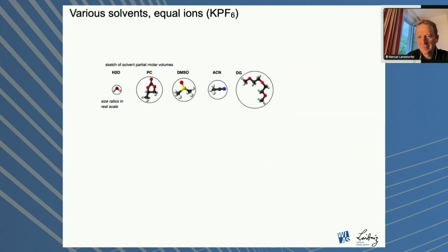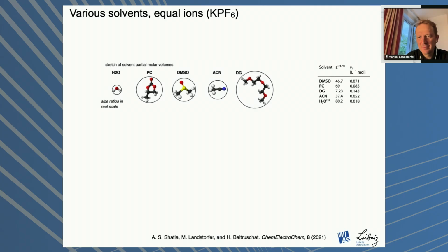I brought a colleague from electrochemistry in Germany, Helmut Baltruschat, into this, and he made experiments on different solvents: not only water, but this whole series of water, PC, DMSO, acetonitrile, and diglyme, all for the very same salt, KPF6, in order to test whether the hypothesis that monovalent ions have similar molar volumes holds true, and also to provide data sets for model validation.